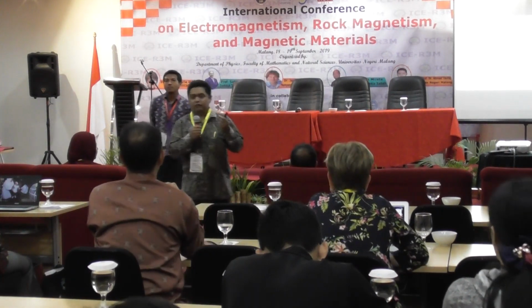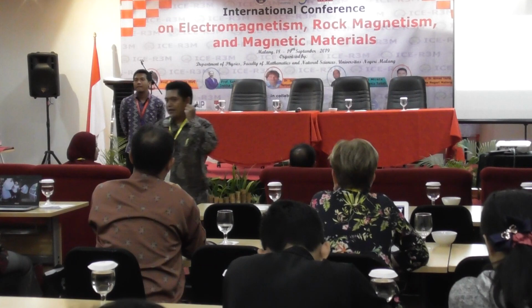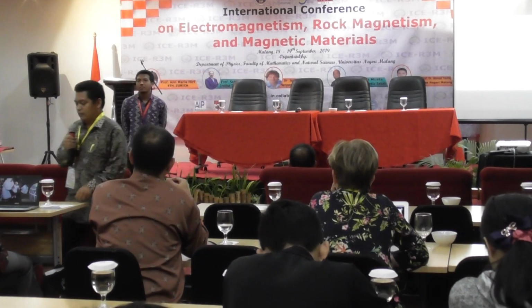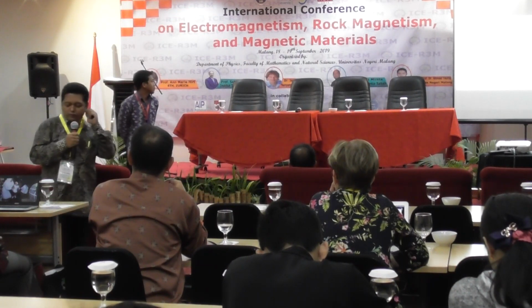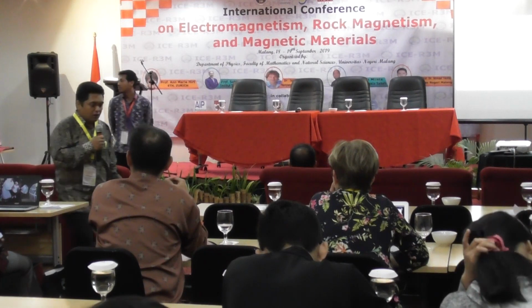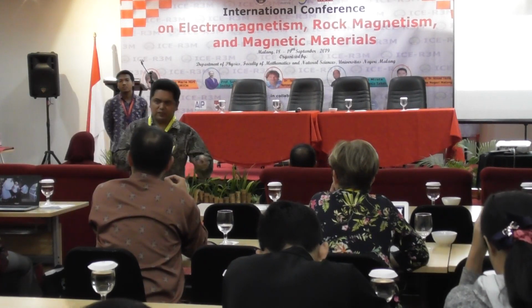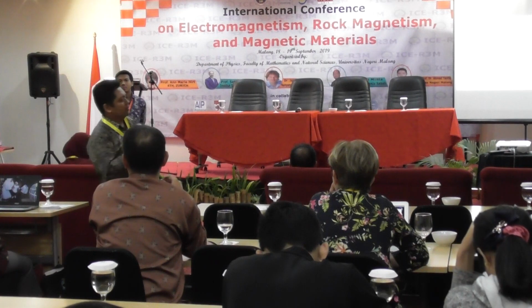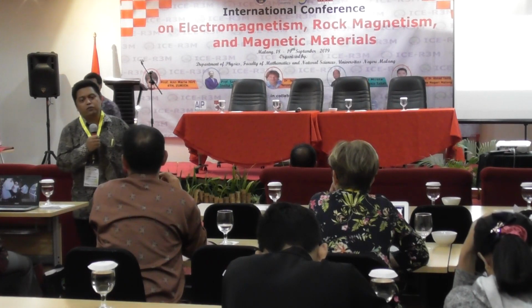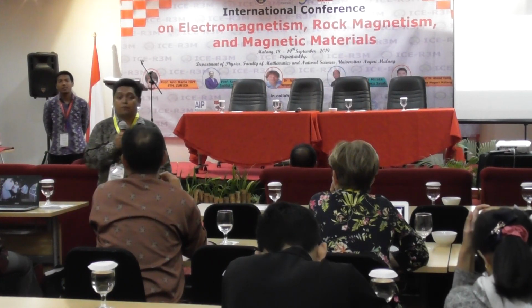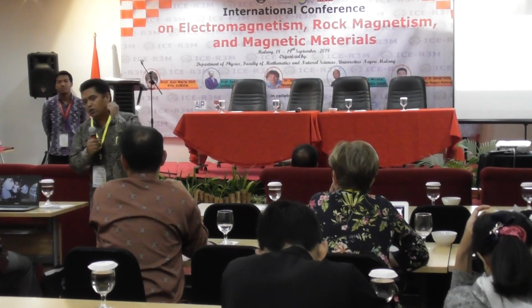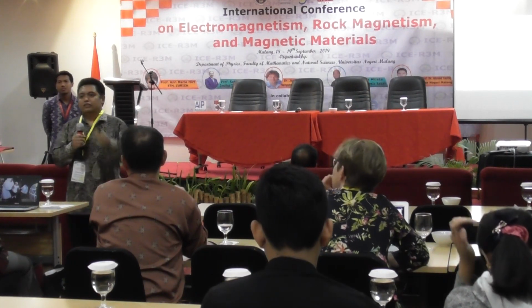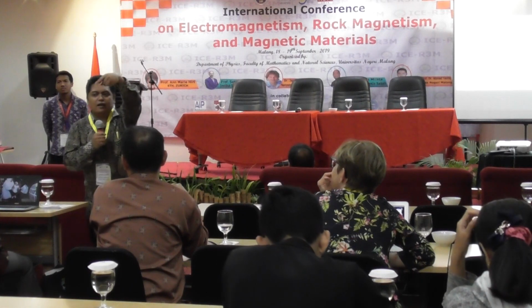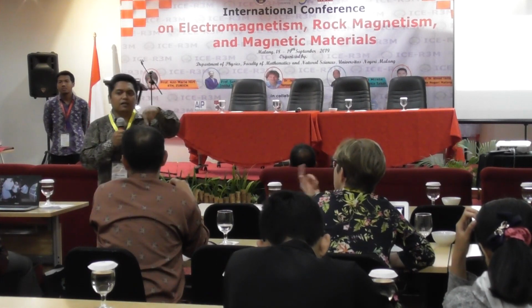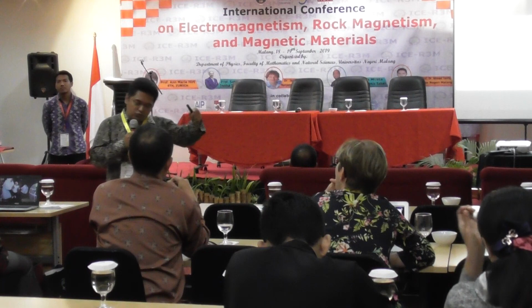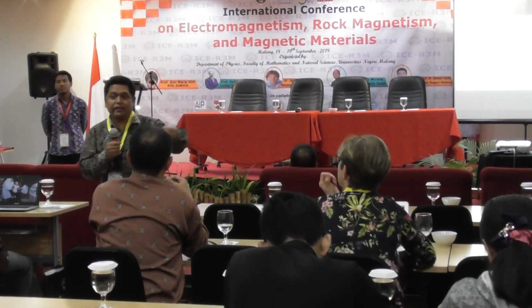In 2009, Dr. Surayono and I, for about 2 or 3 years, synthesized the magnetic nanoparticle using a physical process. We made it by grinding, and also by ball milling, and the last one we used high energy milling.